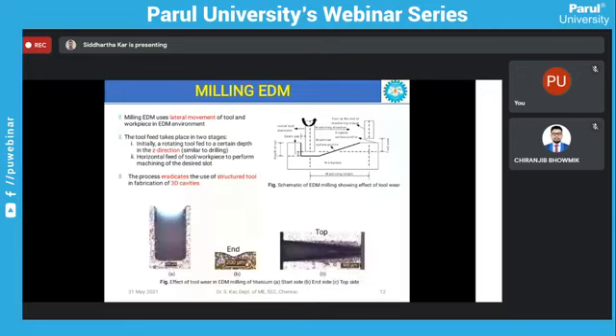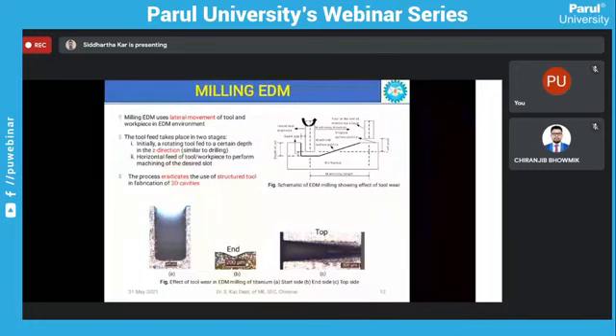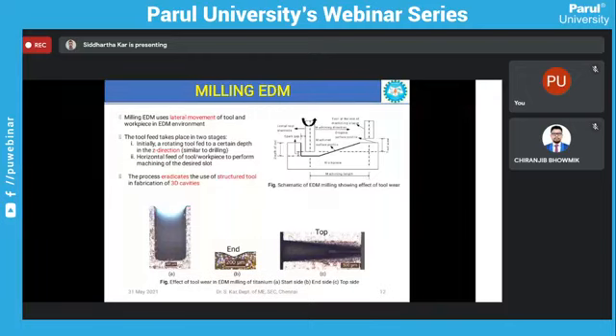Now in this workpiece that has been machined by micro EDM milling process, we can see that at the start, that is figure A, at the start side of the milled slot, the length and the width of the slot is as per our requirement. But at the end side, that is at figure B, we see that the length is very less and the width is almost diminished. Then from the top view, we can see that as the milling slot progresses from left hand side to right hand side, the width of the slot starts decreasing, and it will diminish.